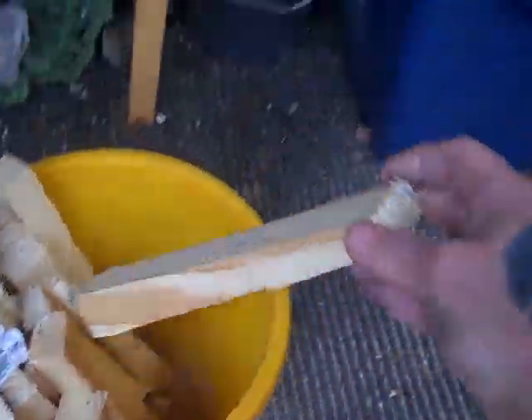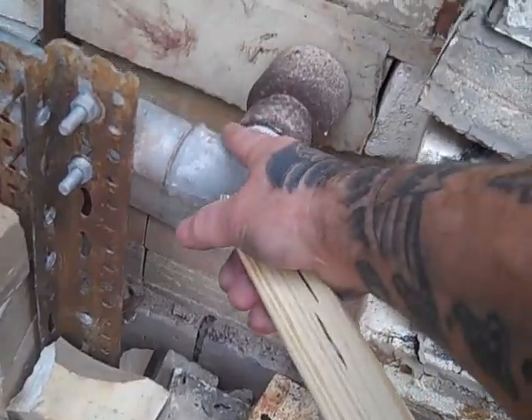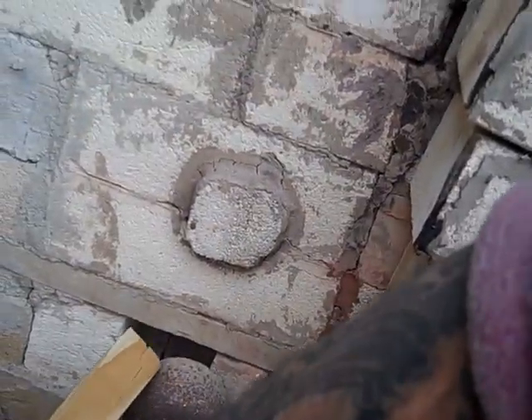There are two reasons I think for that. One is that I left a heavy body reduction well past the 1100°C I normally take it out at — until 1150°C — and then I didn't take it out as much towards the end. Plus I went back to an old style of firing I did a few years ago: I have some wood here, and what I do is I move the burner out of the way and I poke wood into the burner port. It's almost like the end of a wood firing.